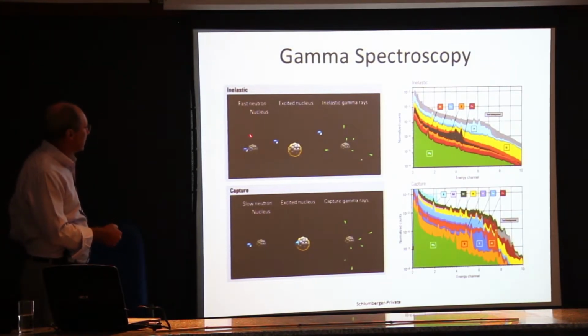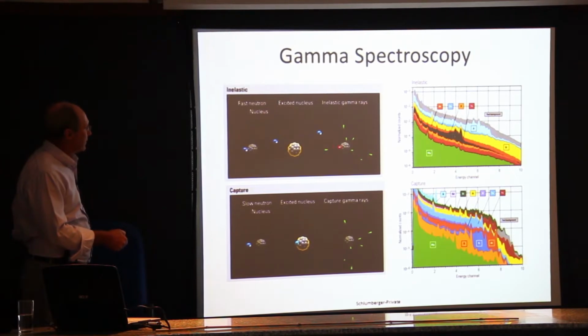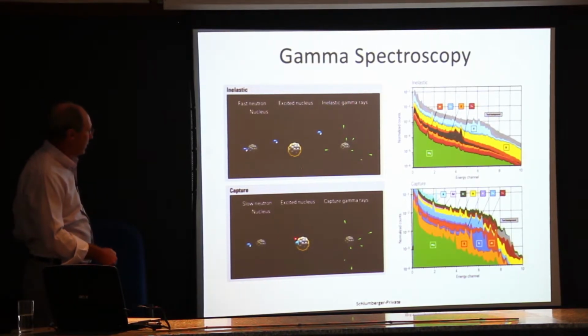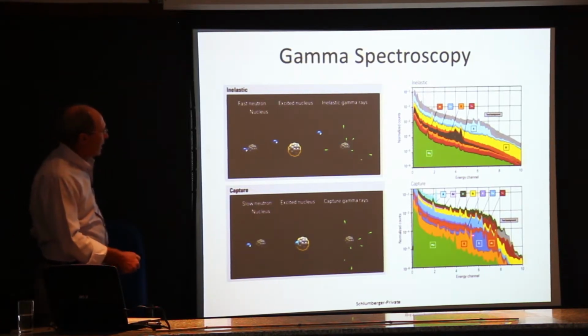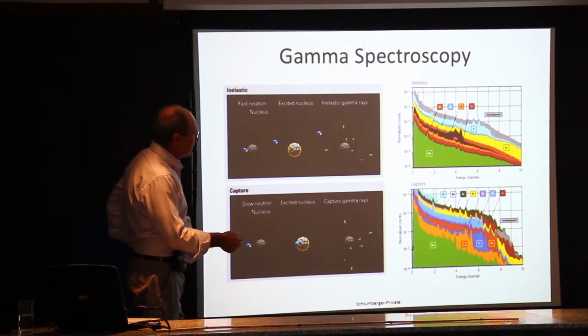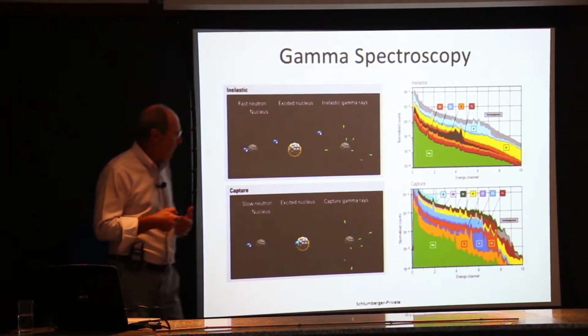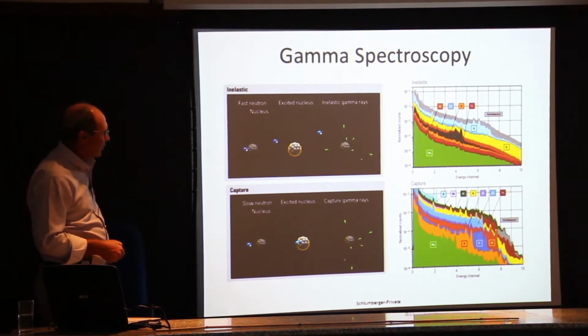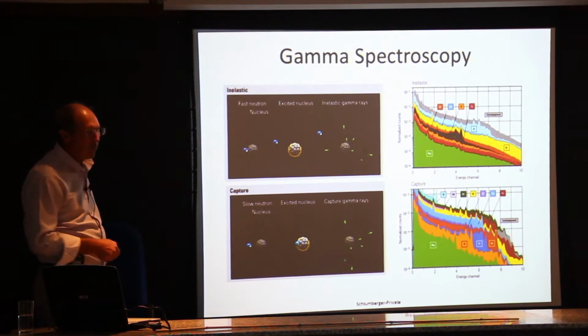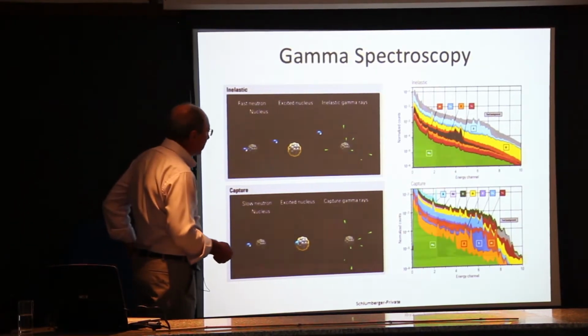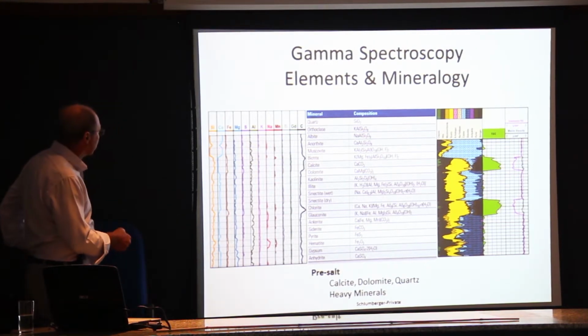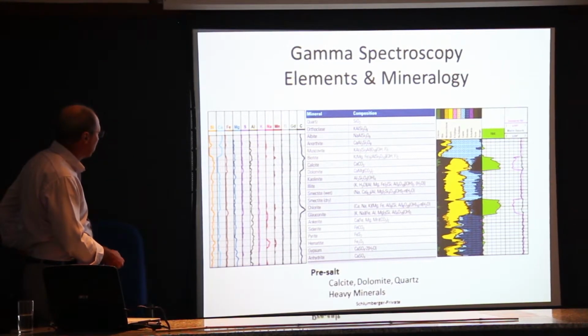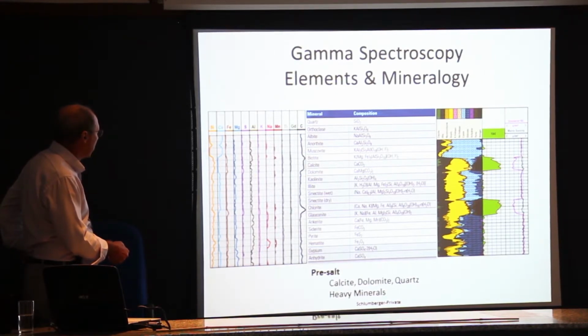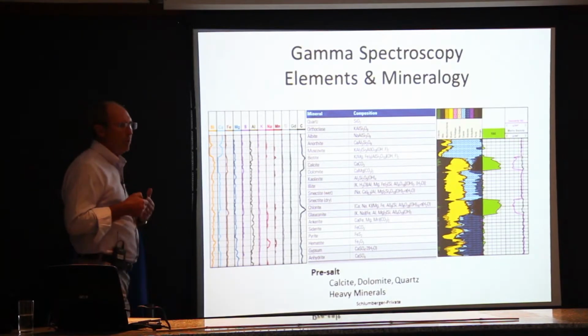much wider use of gamma spectroscopy, and it's used quite a bit now in the pre-salt. As you can see, here's the inelastic energy release in terms of the inelastic gamma rays. Here the neutron is captured and you get capture gamma rays. So different energy levels, and based on these peaks, we're actually resolving the spectra in terms of these minerals. We can actually solve for 20 different minerals. Now this works quite well for the important minerals. Silica tells us how much quartz or chert we have. Calcium tells us how much limestone. Iron tells us what we have in terms of shale.